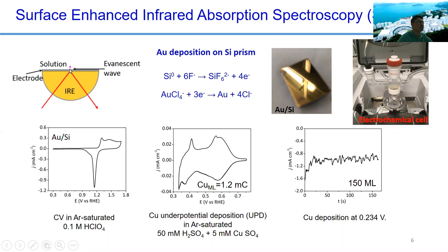So when the infrared is reflected at the interface of the silicon and the liquid, it generates an evanescent wave. It will be totally reflected. Okay, so only this evanescent wave will penetrate through the metal and also the electrolyte. So it's typically less than 100 nanometers. So it's very, very thin, so the effect of the water on the infrared signal is very small. Okay. Another thing is that when you deposit the metal film on this surface, it generates nanoparticles. That film is rough, okay, and the signal can be amplified.